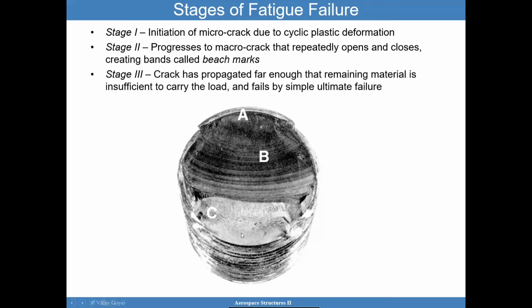Let's look at some stages of fatigue failure. Stage one is the initiation of a microcrack due to cyclic plastic deformation. It doesn't always have to be cyclic plastic deformation. Stage two is one that progresses from a macro crack and repeatedly opens and closes, creating bands called beach marks. And then as the crack has propagated far enough, the remaining material is insufficient to carry the load, and it fails by ultimate fracture or ultimate failure. And so you can see here the three phases, stage 1, 2, and 3, although here it's called A, B, and C.